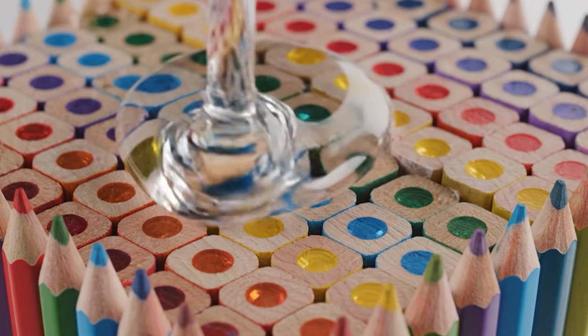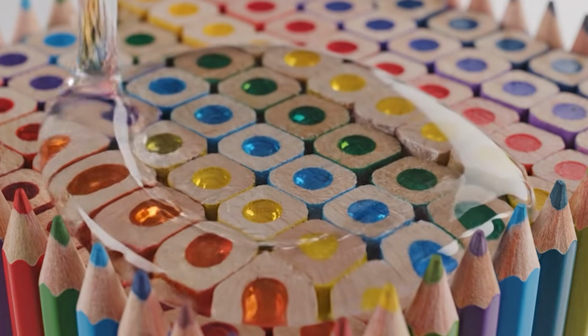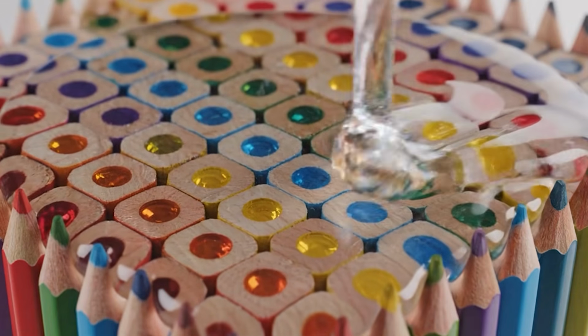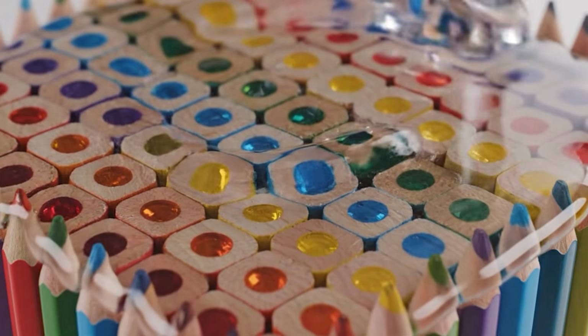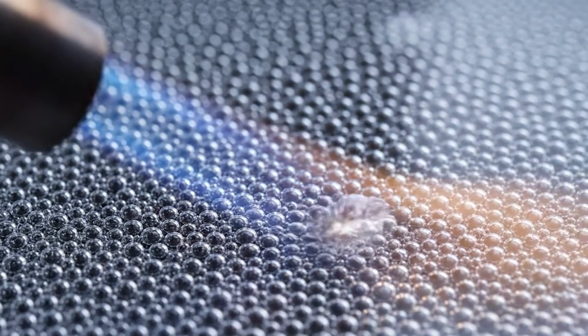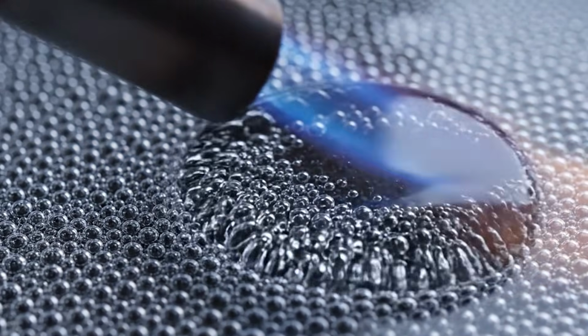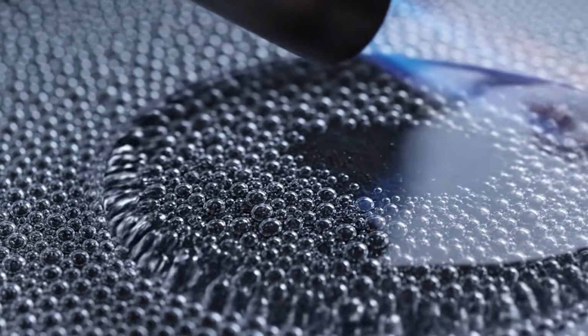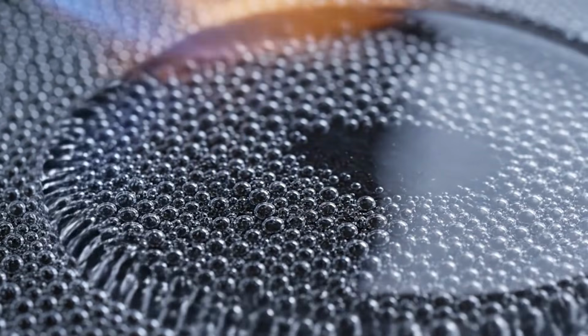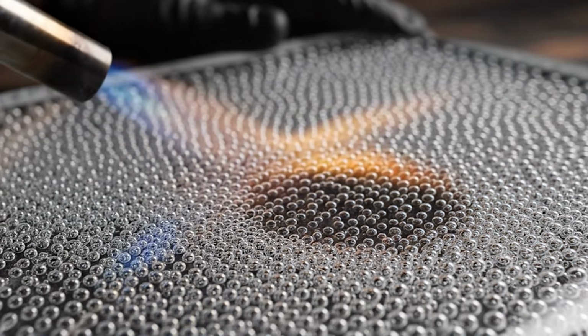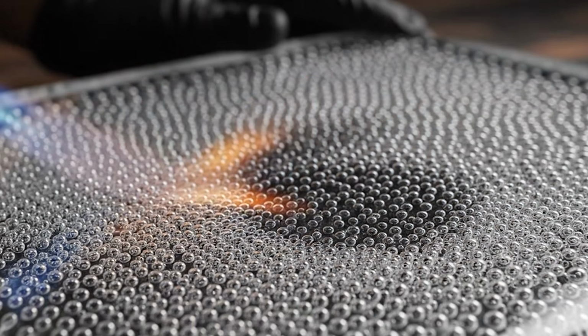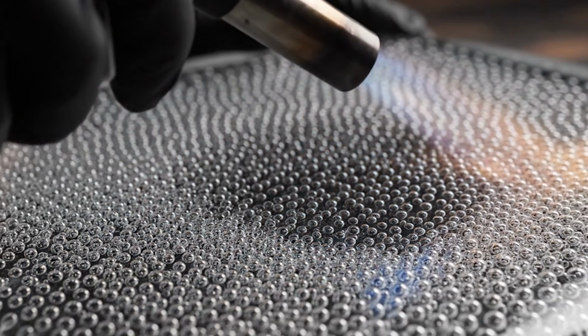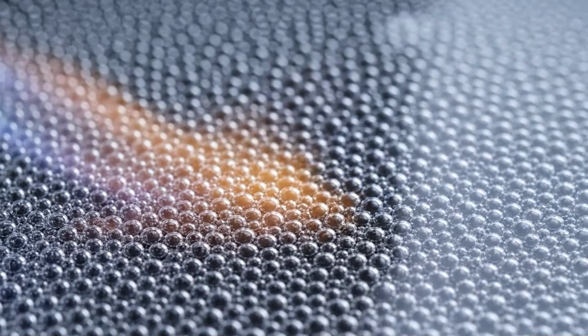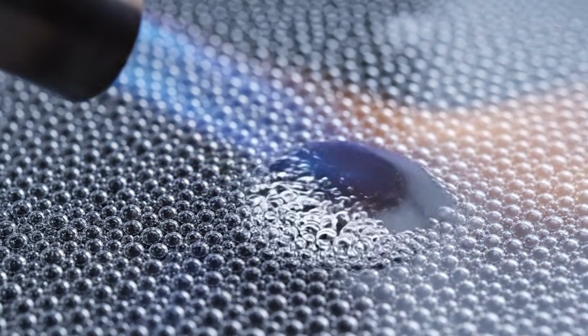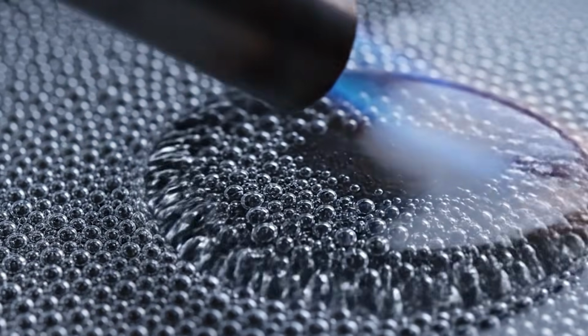Now mix your main batch and pour it slowly into the channel, letting the epoxy flow around and between each pencil. Pour from a low height to minimize bubbles. Once you've filled the channel flush with the top of the slab, grab your heat gun or torch and pass it lightly across the surface. You'll see tiny bubbles rise and pop. Keep the flame moving and never hold it in one spot. Come back and do another pass about 30 minutes later, and then again an hour after that.